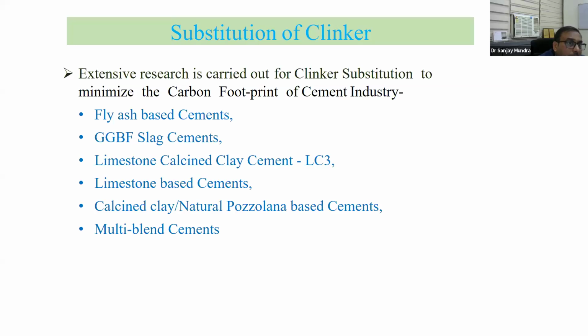Now substitution of clinker, if we have to see the research, normally for reducing the carbon footprint, fly ash based cements, all the industries are using GGBS slag cement. This is the new code developed for LC3. It is very good cement, limestone calcined clay cement. Then limestone based cement, Portland limestone cement, calcined clay and natural pozzolans, and multi blend cements. As I told you, the quaternary blend is also coming with the use of clinker. So ultimately, the aim is to reduce the clinker percentage to less than 45% or 40%, so that we can make a sustainable or novel concrete by reducing the carbon footprint.